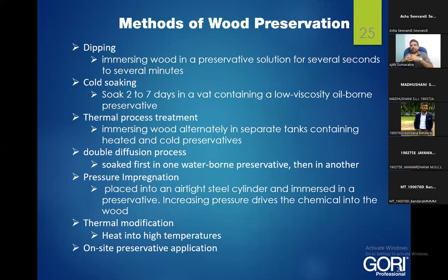Then the second one is cold soaking. In that case, we dip the wood in the preservative container for 2 to 7 days. It is not dipping, it is called soaking. Normally we use a low viscosity oil-borne preservative in this case. Then with time the preservative will penetrate more into the wood and it will give a good resistance.